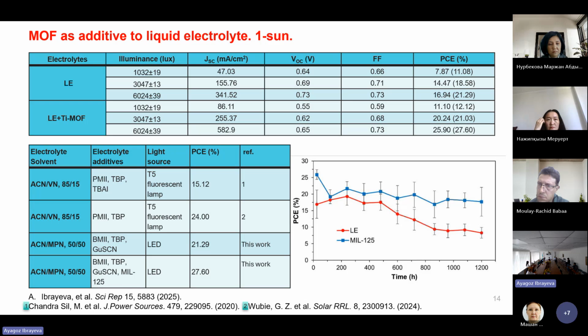Yes, I see the answer. I have one more question here. Please. You used MOF MIL-125, which is a titanium-based MOF, right? What's the difference from other MOF-based solar cells? For instance, what if you used a copper-based or silver-based MOF instead of the titanium one? From the literature data, as on the graph I showed, only aluminum, magnesium, and manganese MOFs were applied, and they also contain polymers in quasi-solid electrolytes. In our case, we simply mix the titanium MOF with the liquid electrolyte and can improve the efficiency and stability. We don't need an additional polymer, and that was innovative.